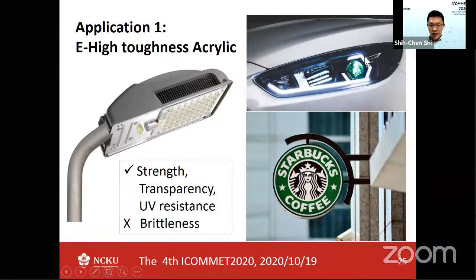And also you can see the car lamp. The outer shape of the car lamp, this material, is normally made with acrylic, or the side board is made of acrylic. But the problem is that acrylic is brittle, so it is easy to break when you ship it or mount it, or even if a bird just hits the side board, it may cause some damage. So we're trying to reduce the brittleness of this acrylic. So the topic is, can we get an extra high toughness acrylic?